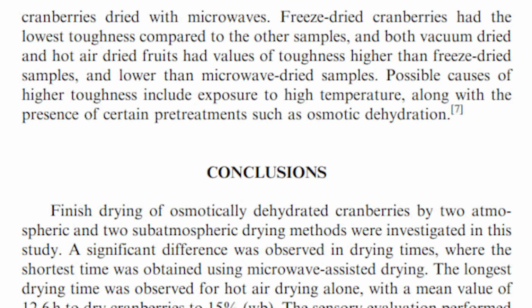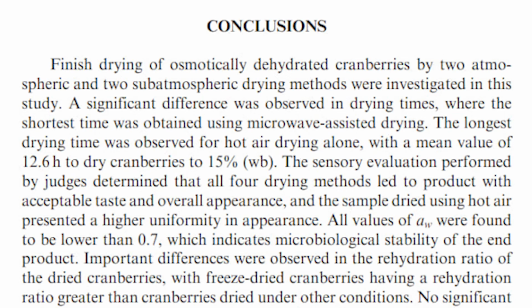Freeze-dried cranberries had the lowest toughness compared to the other samples. Both vacuum-dried and hot air-dried fruits had values of toughness higher than freeze-dried samples and lower than microwave-dried samples. Possible causes of higher toughness include exposure to high heat along with the presence of certain pre-treatments such as osmotic dehydration. Conclusions. Finishing drying of osmotically dehydrated cranberries by 2 atmospheric and 2 subatmospheric methods were investigated in this study.